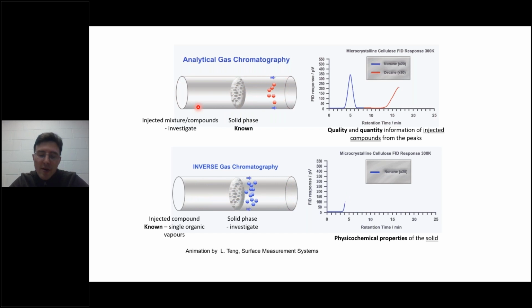The thing we do know very well in this scenario is our stationary phase, our solid phase. We know that this will be something like silica. We know its particle size distribution, its material. We know its dispersive contributions. Therefore, it's very good at separating out my gases. From the location of these peaks and their retention times, I know what that gas is. And from the intensity of these peaks, or the area under the curve, I know how much of that gas there is. So I've solved the puzzle. I found out what it is and how much of it there is.